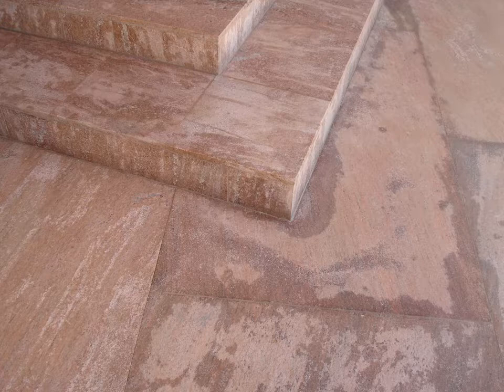And this chloride staining will close the pores up on the stone, and it will not allow the stone to breathe like it should. And then you'll have this problem of spalling as well. Not big pieces, because it's granite. Little tiny pieces are going to flake off, but it'll make the texture more rough than it's supposed to be. This is a flamed texture, so you don't notice the spalling as much, but there were areas where they had it polished, and when it does spall in the polished areas, then it tends to stick out like a sore thumb.